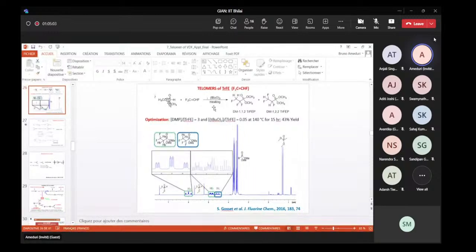So in this case, the proton NMR was very nice and could be well identified, for instance, showing the HA and HB with characteristic signals here and here. And we have a nice example here for NMR of an organic solvent, which was very good to dissolve the lithium salt, TFSI. We published that a couple of years ago, showing also that the residue of distillation had some telomeric distribution.